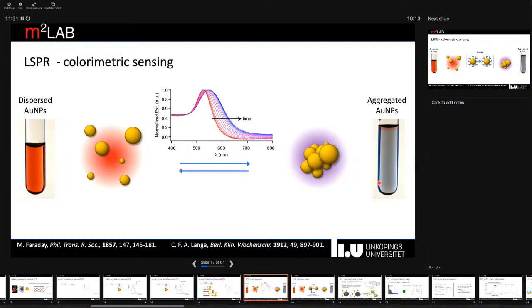Anyhow, a few years later, in 1912, Carl Friedrich Lange published a paper on using this phenomenon as well, the aggregation of particles and the optical coupling and the resultant color change, for diagnostics. So also, to my knowledge, the first nanoparticle-based biosensor. And he used this phenomenon for diagnostics of patients with syphilis. So essentially taking cerebrospinal fluid from these patients and subjecting it to gold nanoparticles. If you had syphilis, they started to aggregate. If you were healthy, they did not, for some reason. And this test was used for quite many years in the clinics.